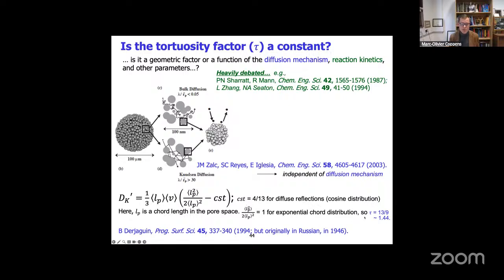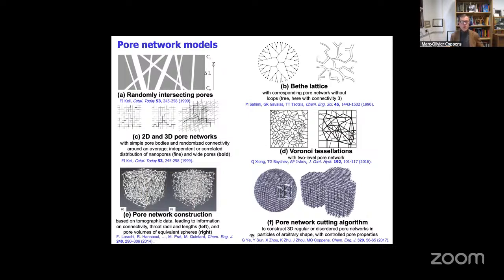And so that's really a reason why these tortuosity factors tend to be around less than 2, right? So for this type of material. In other cases, again, you will have to deviate from that. And so there's a whole range of pore network models that go into the details of including intersections between pores, full pore network models with pores of different pore sizes. And sometimes the older models would include narrow pores and broad pores, calling them micro and macro, but they might actually be mesopores that are narrower or broader.